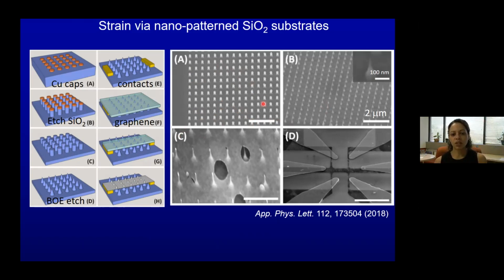So you can see here that we go from these square pillars to these very sharp pillars when we do an etch. We then put on contacts and the graphene, and suddenly we have a device where the graphene is suspended on these very sharp pillars, and it's patterned for transport.